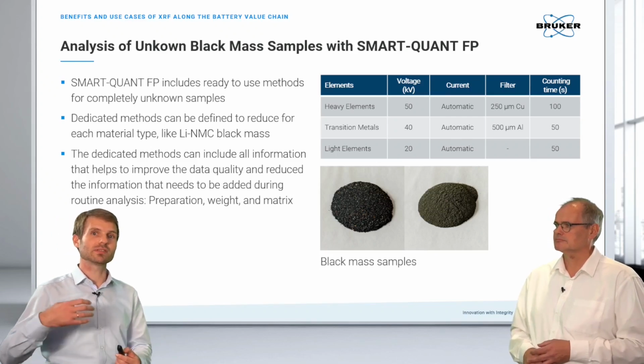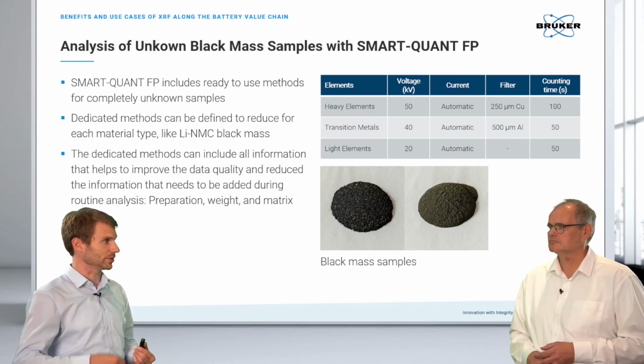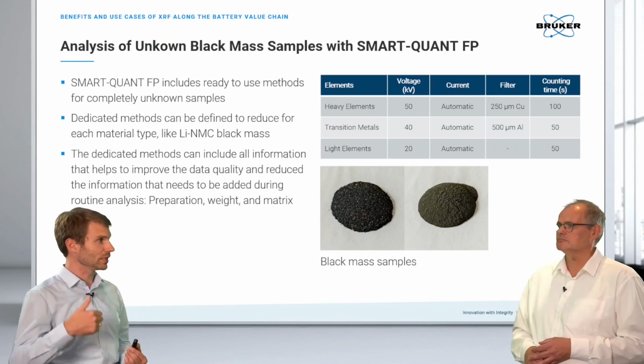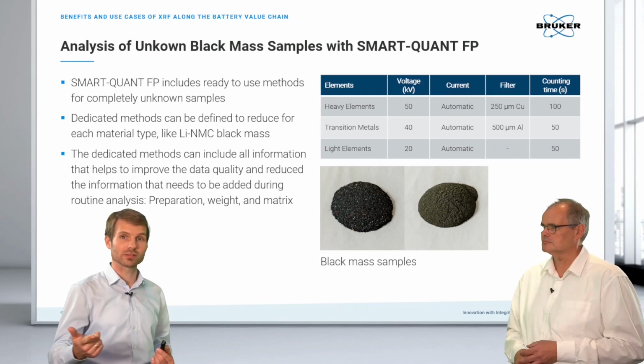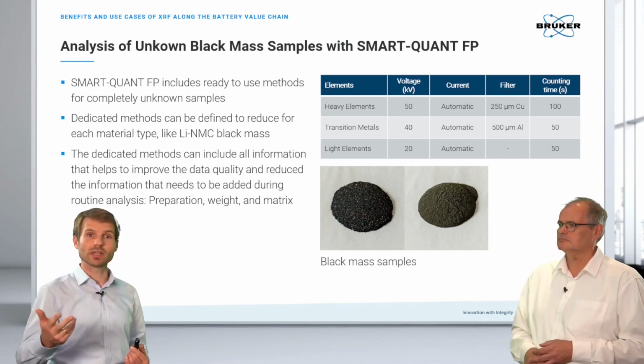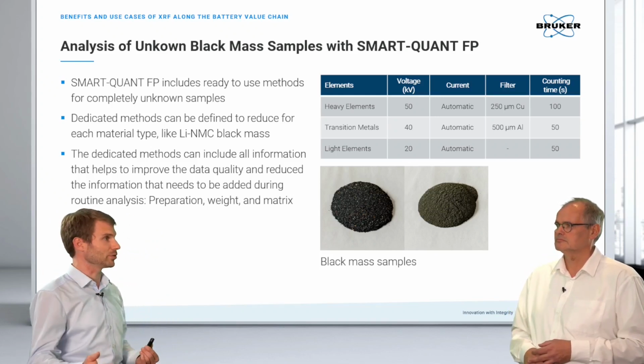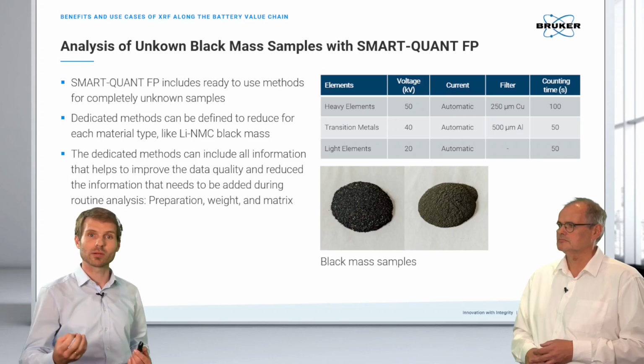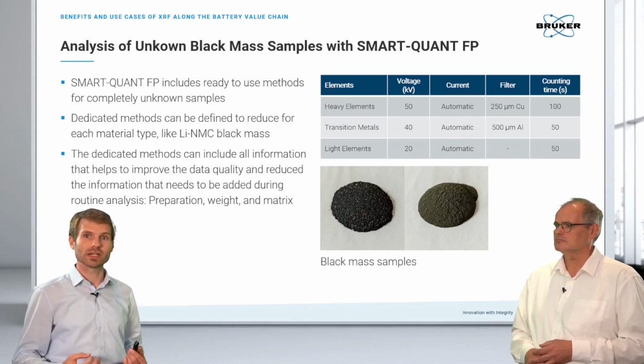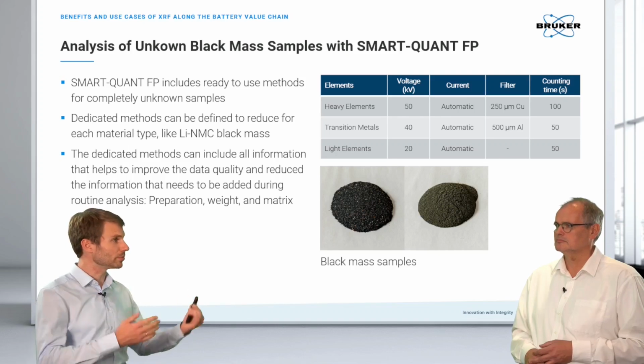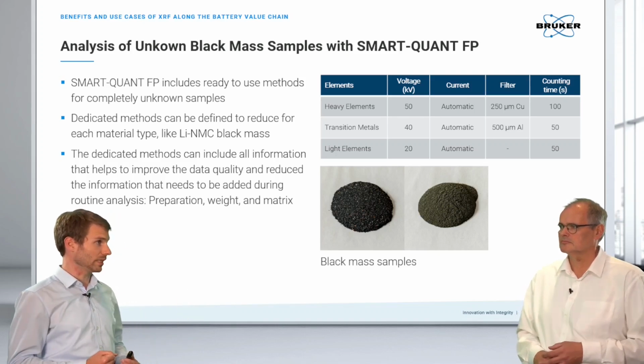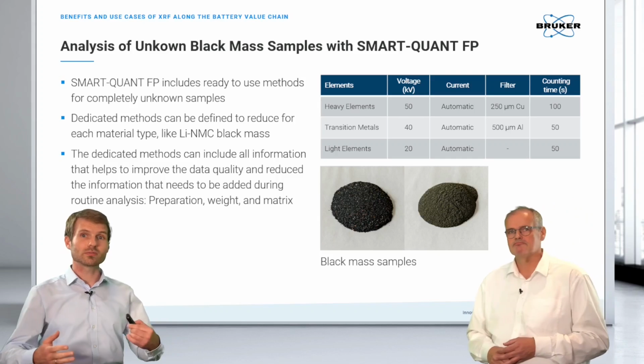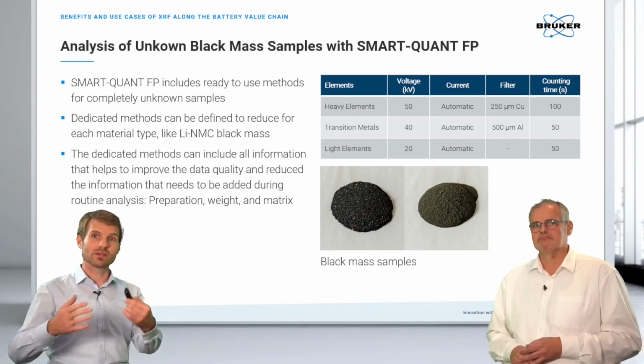SmartQuant comes with some ready solutions, for example, to measure oxide, smart matrix, but you can also fine-tune it. So you can give it some more information about your sample. You tell it, for example, it's a powder, I added so many grams into the sample, and I know that in a black mass my matrix should be something carbon, so it should probably be graphite. If you enter that material, you will improve your data quality.